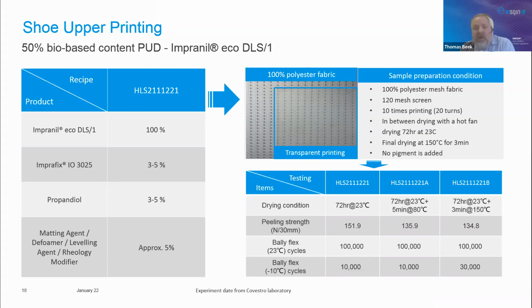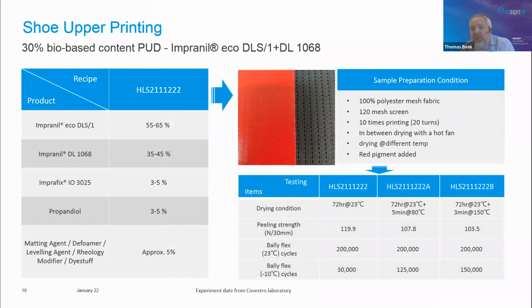Besides the 72 hours drying at room temperature, we also did a forced drying at 80 degrees for 5 minutes, and in another trial we ran a forced drying at 150 degrees for 3 minutes. As you can see in the picture, that was a transparent printing application, only to show you that we can do transparent printing with this system. With the inclusion of the crosslinker and the forced drying at 150 degrees, we could improve the cold Bally flex behavior strongly. On the next slide, I will show you a possible way to combine the bio-based PUD with the standard waterborne PUD.